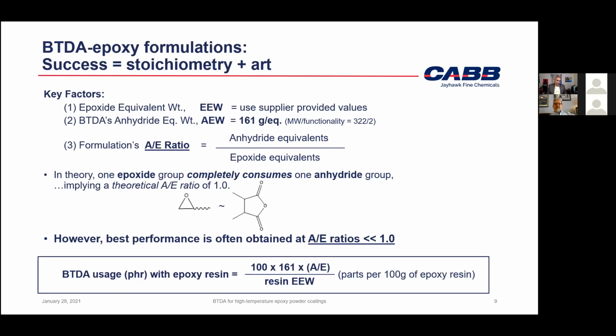I mean, this is one way. And just to give you an idea, if you have 100 grams of your chosen epoxy resin with a defined EEW that you know from the supplier, and you have the equivalent weight of 161 for BTDA, then this equation will give you the amount of BTDA to use in the formulation for 100 grams of epoxy resin, PHR sometimes we say. And there is this important fudge factor, or I guess artistic calculator factor that we use, which is the A/E ratio in the formulation.